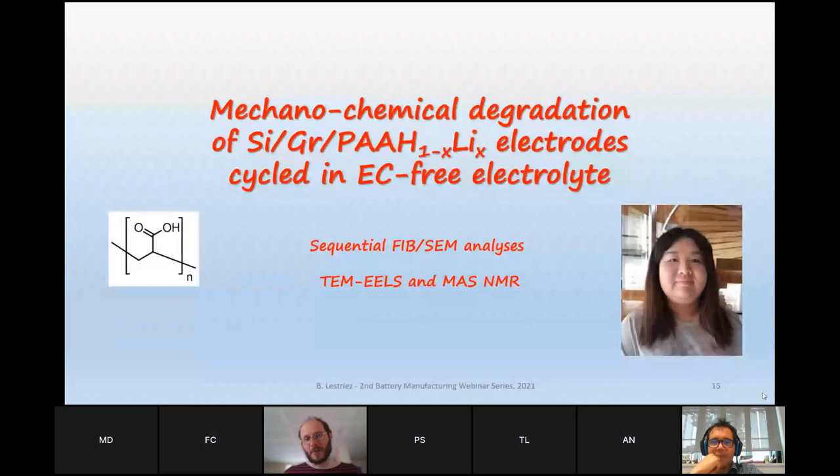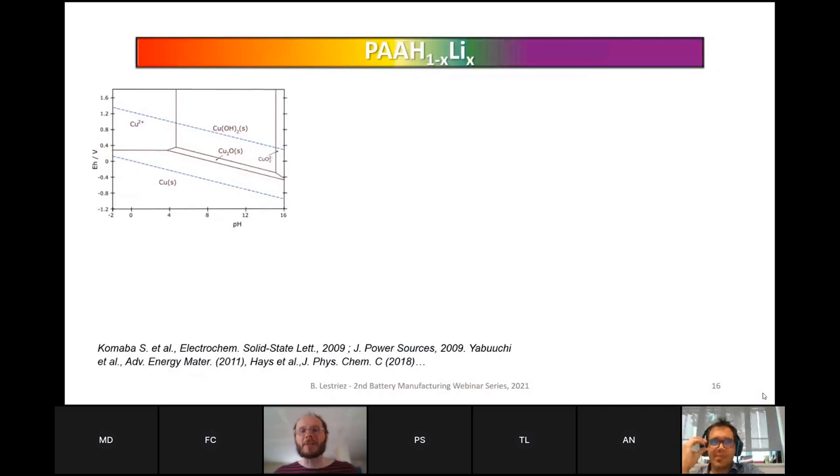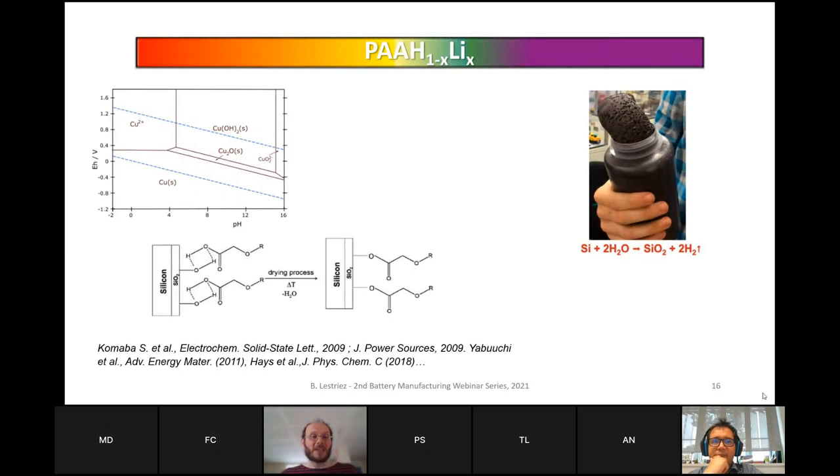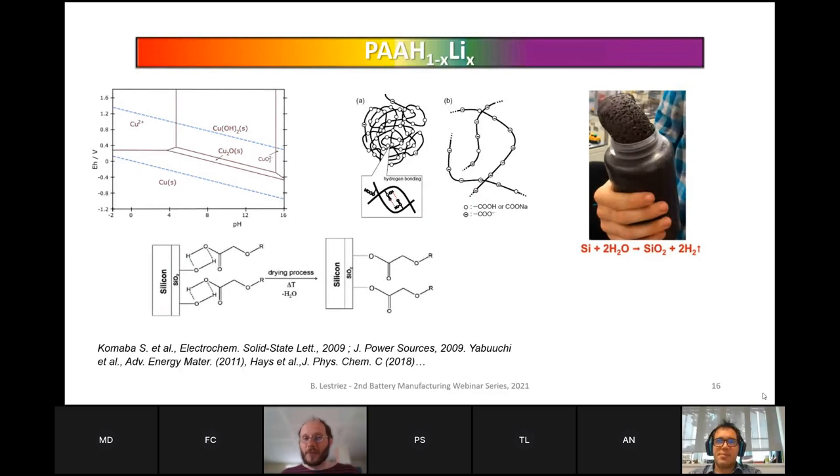Next. So again, the pH was a strong parameter of the study because we know that the copper can be corroded at acidic pH. Next, while in neutral conditions we have silicon oxidation, which may release hydrogen, which is very detrimental if you consider industrial pilot fabrication lines. Next, we expect also, depending on the pH, different interactions between the binder and the silicon, and in particular grafting in acidic conditions. Next, we also expect different conformation of the polymer, because in acidic conditions, due to hydrogen bondings,